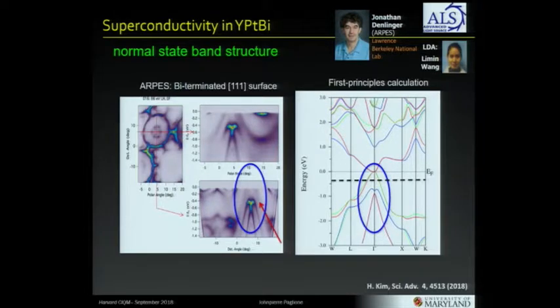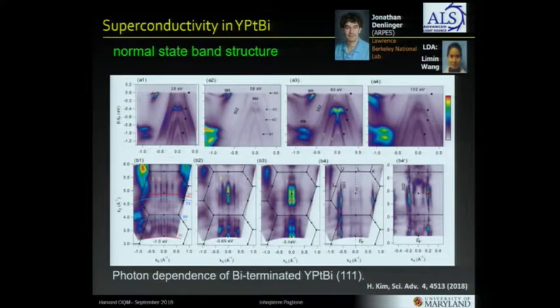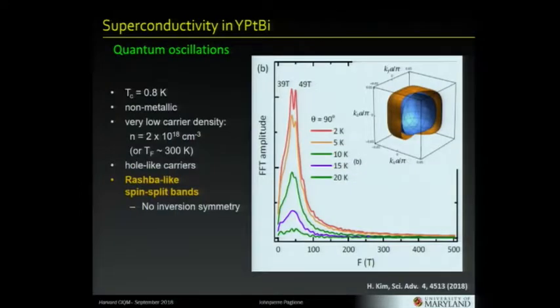We know from quantum oscillations, which is a stricter measure of the Fermi surface, that these guys aren't around. So we think this is just an artifact of the photoemission study. I won't go into this, but this is just a photon energy dependence study showing that these bulk bands right here are indeed bulk-derived bands. And so that matches the expected band structure.